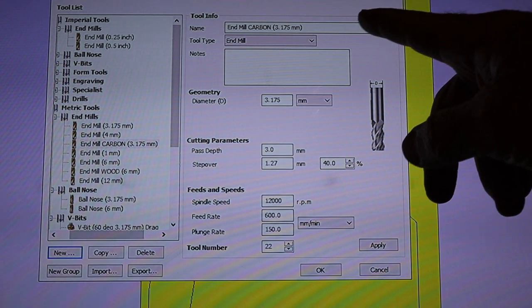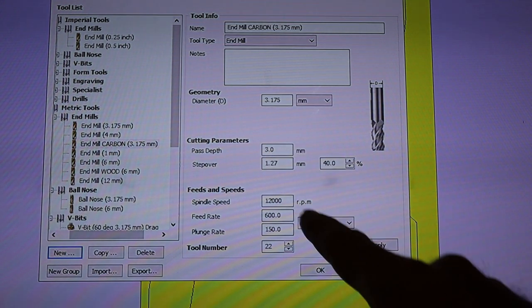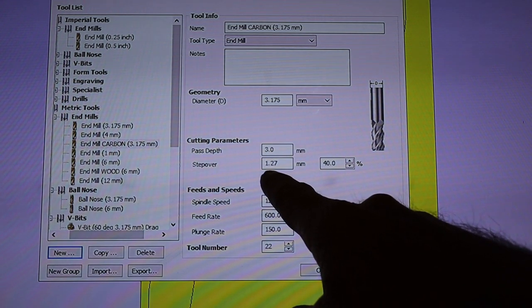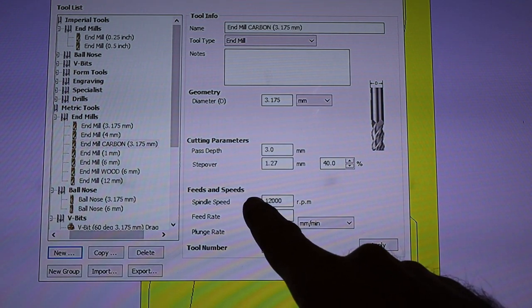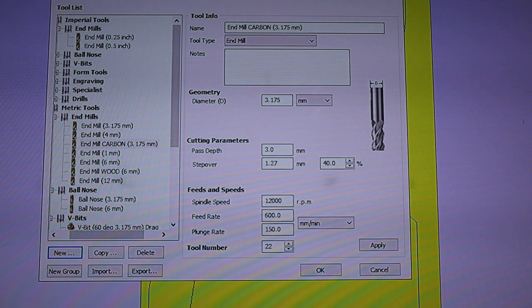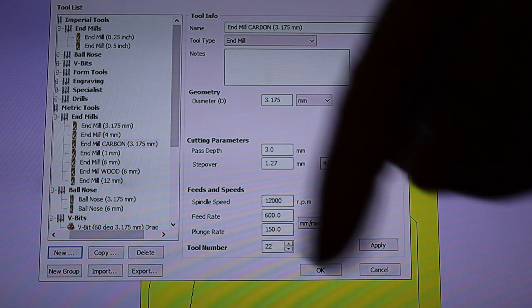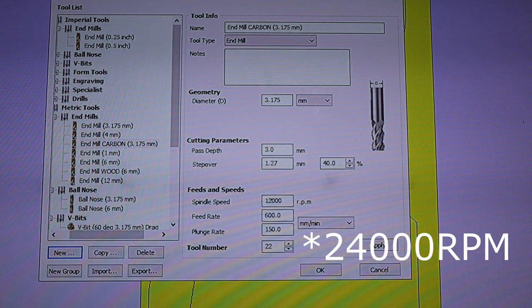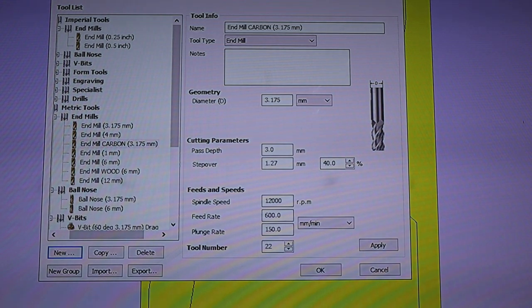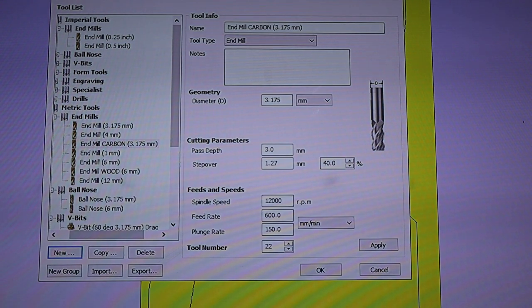I'll just run through and show you the settings I have for the cutter. 1/8 inch cutter. It's 2mm thick carbon that we're using today, cutting full depth. Don't really need to worry about the step over in this case, but I just have 40% generated on that one. Spindle speed I control at the machine. I don't know the RPM off the top of my head, but I'll pop it on the screen here. Feed rate of 600mm per minute and the plunge at 150 seem to work really good at getting a good surface finish and keeping the dust located in the joint which I'll show you shortly.